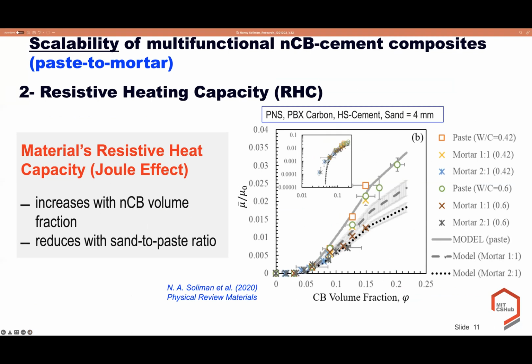One of the most attractive applications of electrical conductivity is resistive heating capacity. And here we establish a fantastic relation between resistive heating capacity and volume fraction of nanocarbon black for different pastes and mortars produced with various water-cement ratios and sand content. What we observed is that the Joule effect increased with the addition of nanocarbon black while reduced with the sand addition. And this relation is so important when we design a material with resistive heating capacity, as it quantifies what we should know when we design our material: how much carbon should be added, and how much this effect is diluted by the addition of sand.